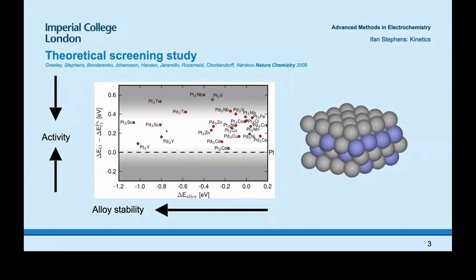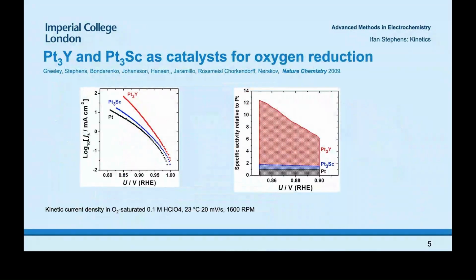So I was really disappointed, and I thought, okay, I want to try these other platinum-based catalysts, but first I want to really get the platinum measurement right. So I went through that process, and then I went on to measure platinum yttrium and platinum scandium. And actually, it turned out that platinum yttrium in particular is much more active than platinum. This time, looking at the kinetic current as a function of potential, the platinum yttrium was the most active catalyst tested in this way reported in the literature.